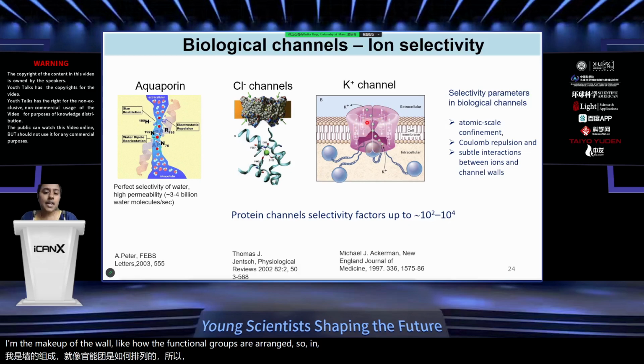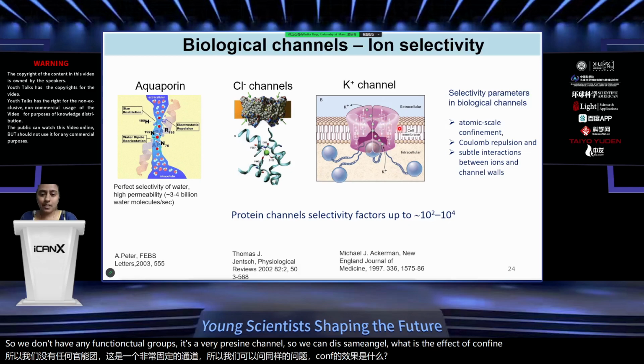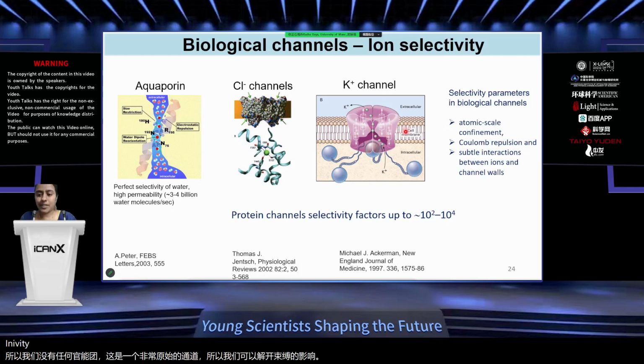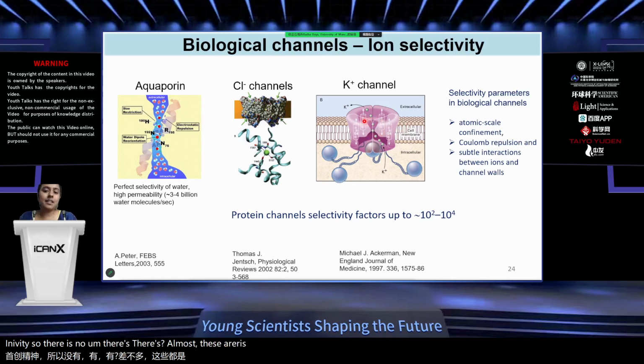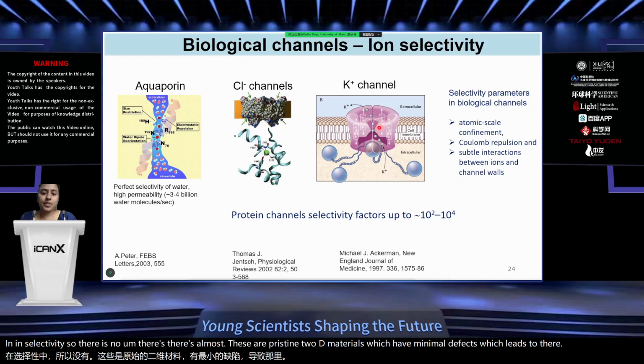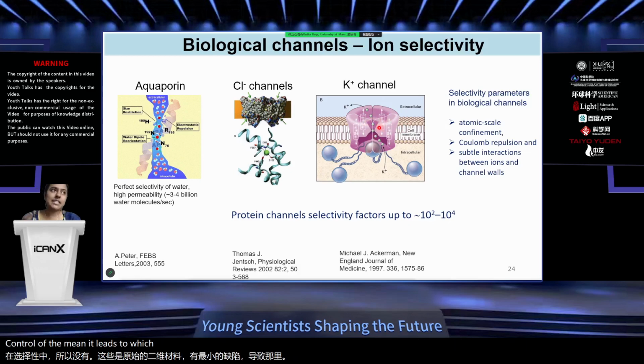So in our case, we have at least a very good control of the confinement dimension. So we don't have any functional groups. It's a very pristine channel. So we can disentangle what is the effect of confinement in selectivity. These are pristine 2D materials which have minimal defects, which leads us to study the effect of geometric confinement.